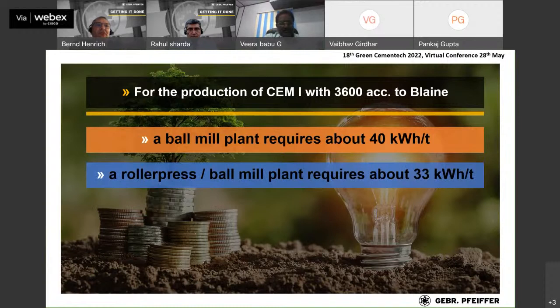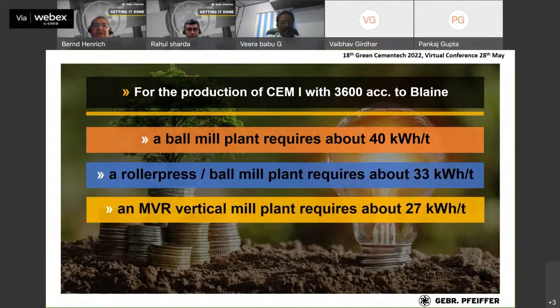The optimization by using combi grinding systems, roller presses in front of the ball mill, gives a significant reduction in the electrical energy. Sure, the next step is the vertical roller mill, let's say the state-of-the-art efficient grinding system, where we can come down from roughly 40 kilowatt hour per ton to 27 kilowatt hour per ton of clinker cement grinding, the OPC grinding.